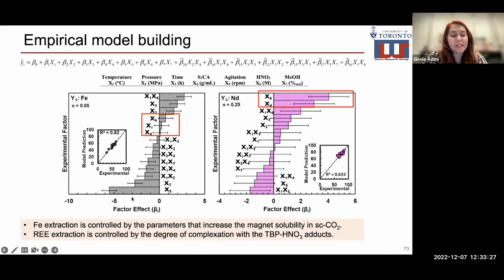Here we see graphs of the effect of operating parameters on two metals, iron and neodymium. Neodymium is the representative of neodymium, praseodymium, and dysprosium. Here we build empirical models that connect the extraction efficiency of each metal to the operating parameters. The bars on the right-hand side of this graph show the parameters that have positive impact on the extraction efficiency, and the ones on the left show negative impact. Any bar that has the error bar crossing the zero line has statistically insignificant effect. And these graphs in the inset show the model prediction results versus experimental results.